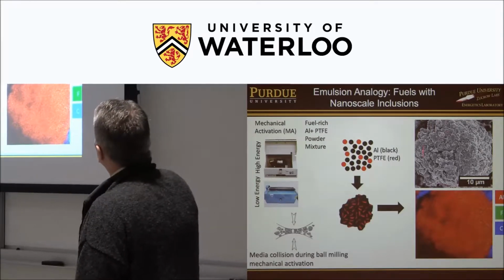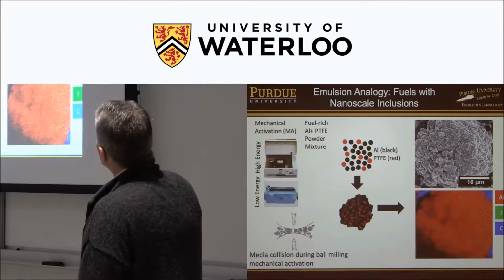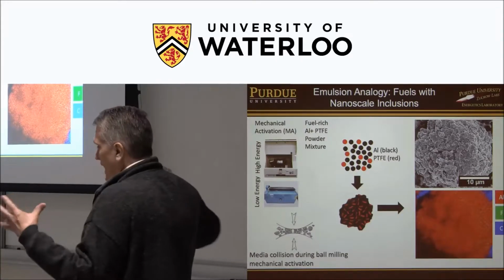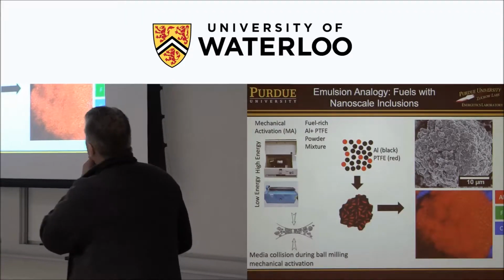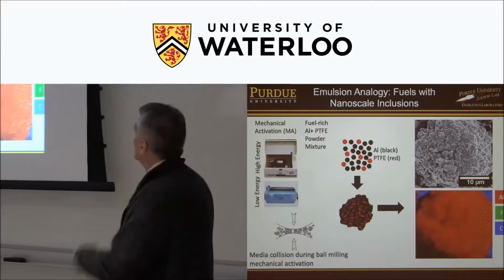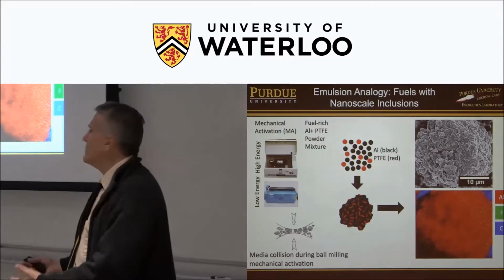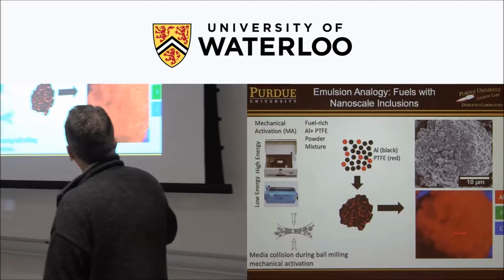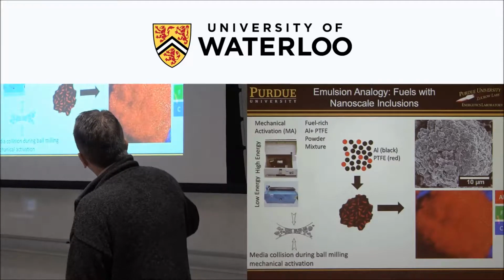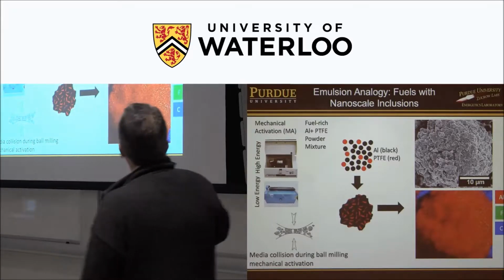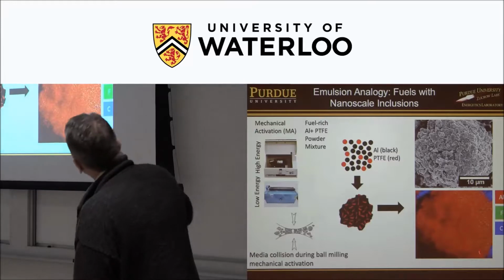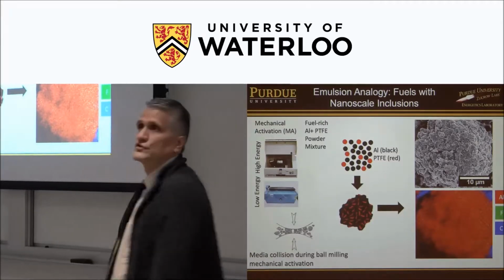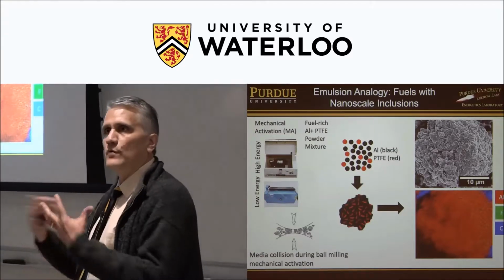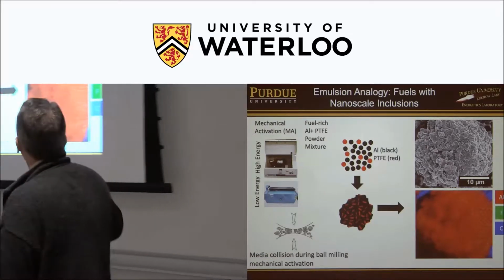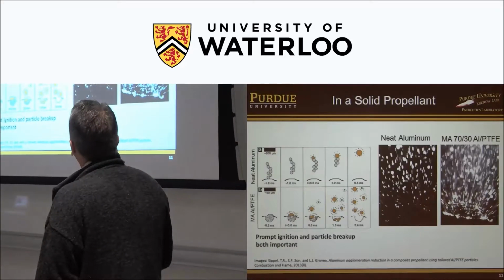This is an SEM image of that particle. This is 10 microns. So it's actually micron sized, which has advantages in that it could be a drop-in replacement for just aluminum powders. This is looking at the EDS, the energy-dispersive spectroscopy. The green here doesn't show up too well, but it's very well dispersed throughout that particle. So we've got Teflon throughout that particle, and it is a nanoscale inclusion.